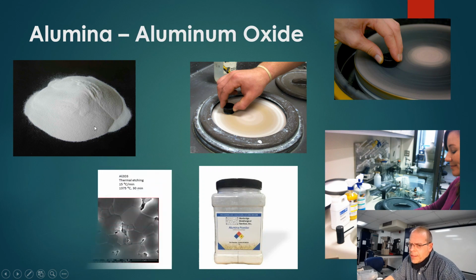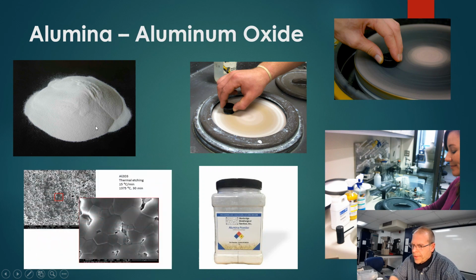What we're going to do is compress this together like a snowball, and we're going to try to make a ceramic composite out of it, going through a series of steps. What you see in the bottom corner over here is an SEM picture of an alumina puck I pressed together. This is taken in the scanning electron microscope, so you're actually looking at size in nanometers. I just want to point out these little openings here. These are all pores, and this porosity is going to play an important role in a couple of different functions along the way as we go through this.